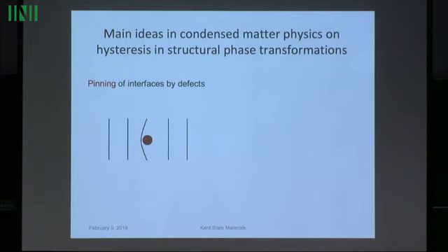And the interface comes up against this defect, and maybe by lowering the temperature, you're making one phase more favorable, lowering its energy well by controlling the temperature. When the interface comes up against this non-transforming defect, it requires an additional lowering of the energy well of this phase, or an additional lowering of the temperature to cause this interface to break through somehow.